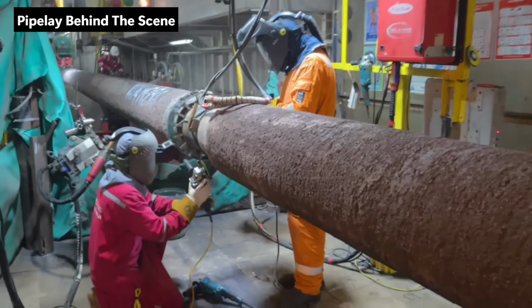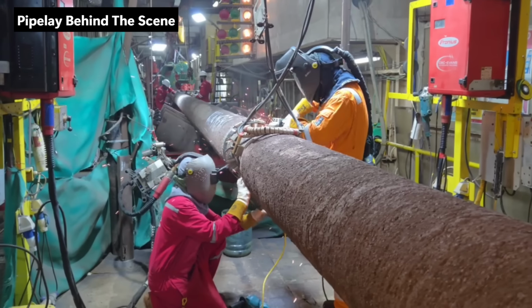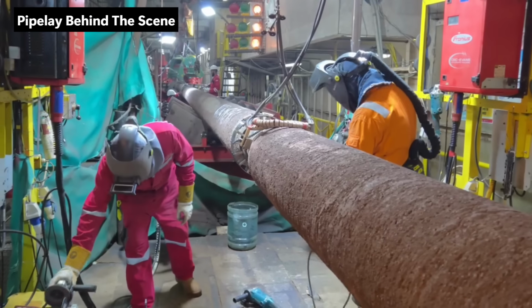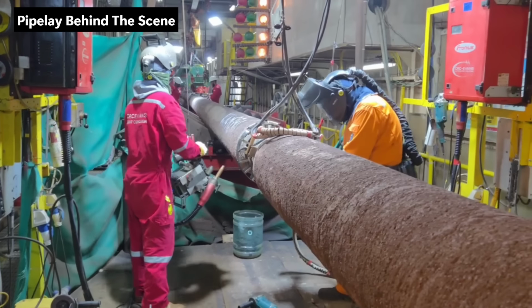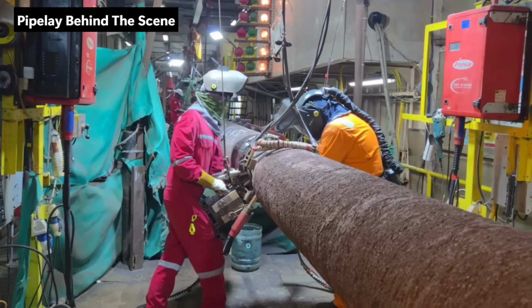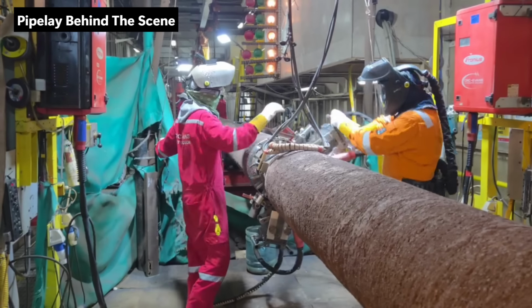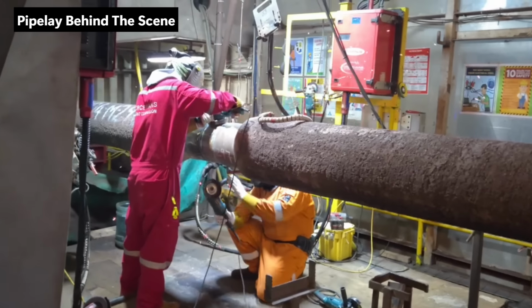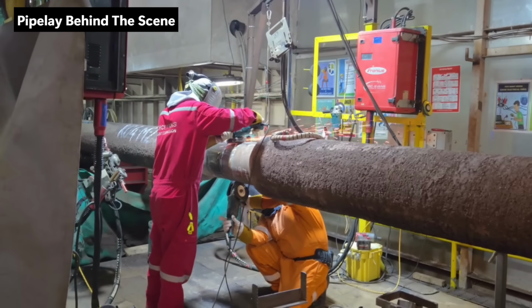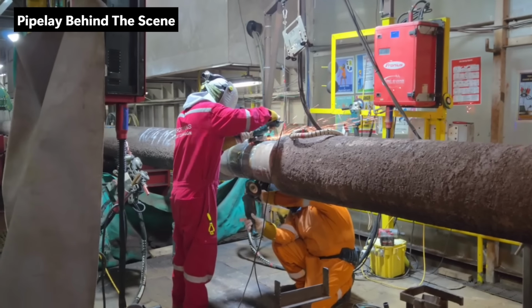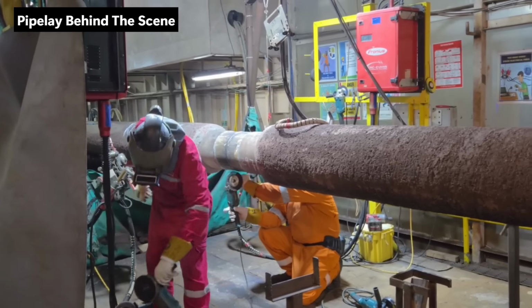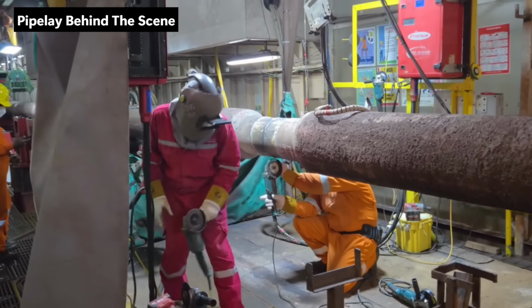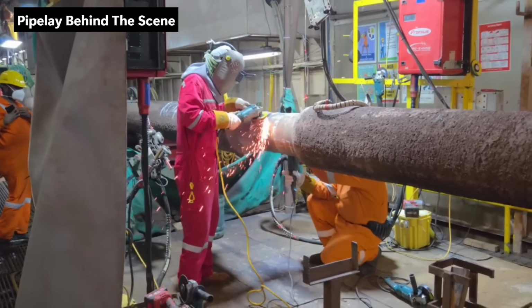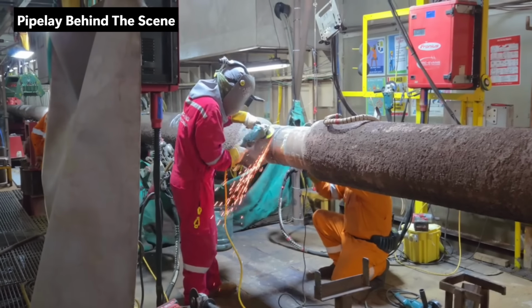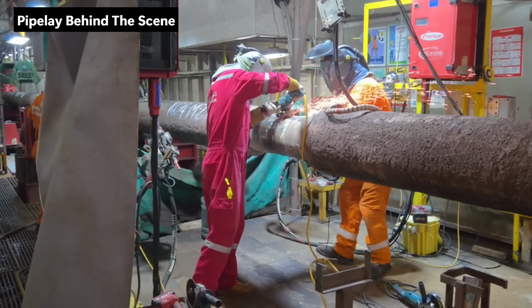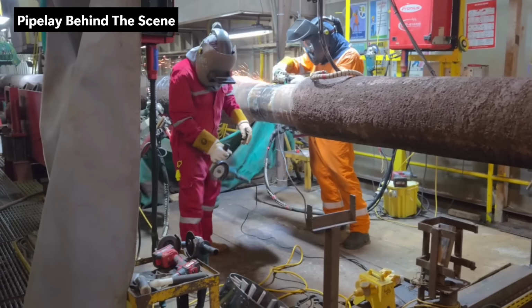The pipe is now moved to the third welding station. The earlier passes fill most of the bevel. The work at this station is to complete the fill and put down the cap, the final weld pass that you can actually see on the outside of the pipe. Between each weld layer, the surface is cleaned. Wire brushing, grinding. This is not just tidying up. Each layer must be cleaned before the next one is deposited. Otherwise, you are welding over contamination, and that creates defects inside the joint.